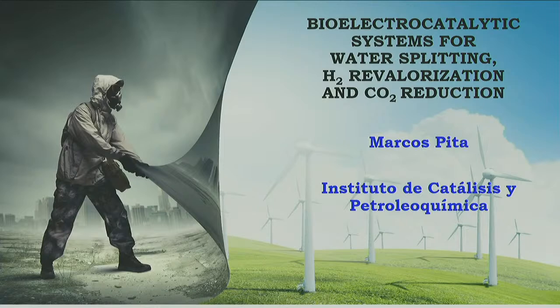So how do you deal with this with aspect? You are completely correct, and we try to avoid multipunctual immobilization. We normally use single point immobilization through a covalent bond, and we still lose activity. Probably the enzyme is slowed down because of these steric restrictions. We also, especially with these systems related with semiconductors, not only with electrodes, some of the enzymes, especially hydrogenase, work better if we don't immobilize it, because the material is extremely porous.